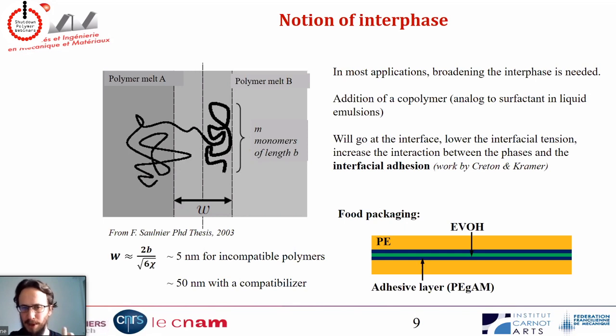properties. But if you add a compatibilizer, which is usually a copolymer, it will segregate at this interface. So it will expand the size of the interface. Maybe you can have 50 or so nanometers as an interface, which is above the entanglement size, which means that you will have some interfacial adhesion between the two phases, which means that your film can have good properties.